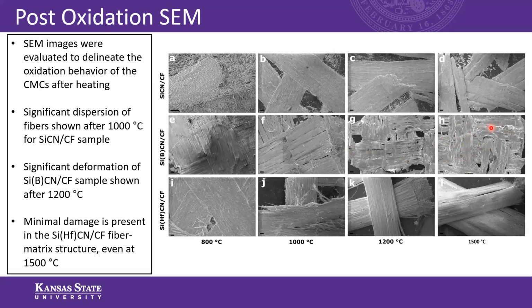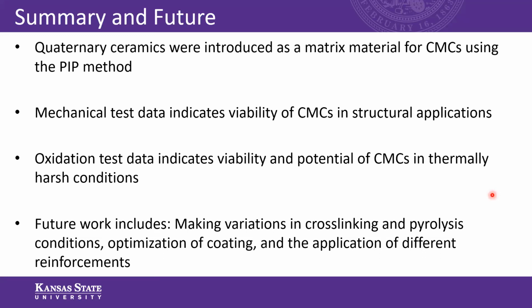But comparatively to the other two, the SiHFCN sample had minimal damage present. As you can see, the matrix structure of the fibers survived and is visible at 1500 degrees C. So to conclude, quaternary ceramics were introduced as a matrix material for ceramic matrix composites using the PIP method. The mechanical test data indicates the viability of CMCs in structural applications. Oxidation test data indicates the viability and potential of CMCs in thermally harsh conditions.